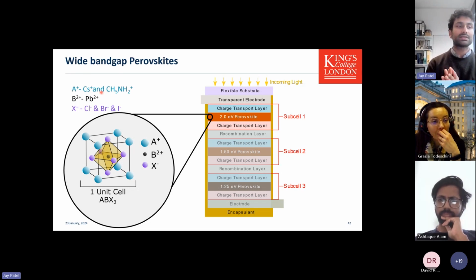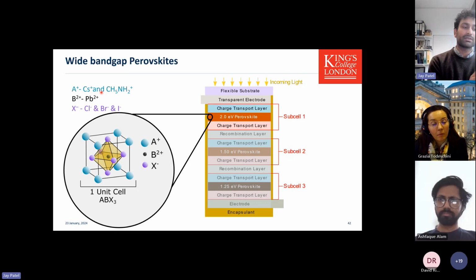And the reason for this is, yes, solution techniques work, but it's not shown to replicate what you get. Solution-based techniques give the world record in the lab. But when people have tried to replicate that on a larger scale using inkjet printing or spray pyrolysis, they've not been able to replicate such success. Whereas PVD has not shown the highest of efficiencies, but reliably, when it's gone into a larger module size or industry, it's shown to be of a good efficiency reproducibly.